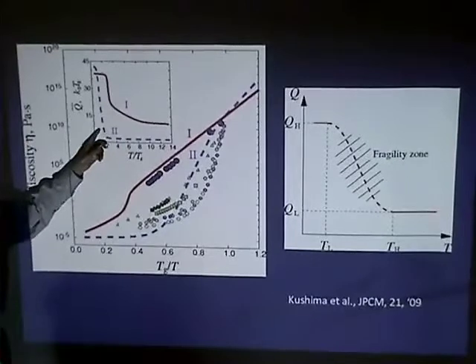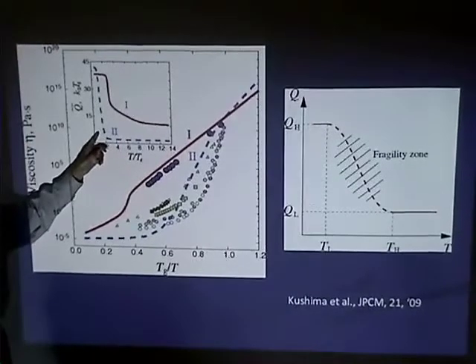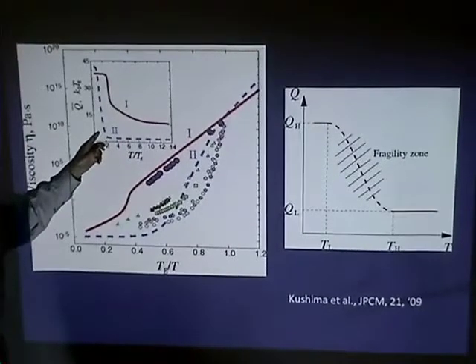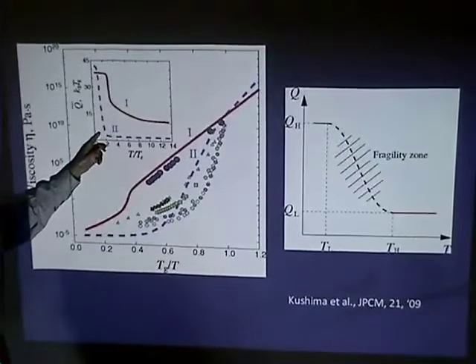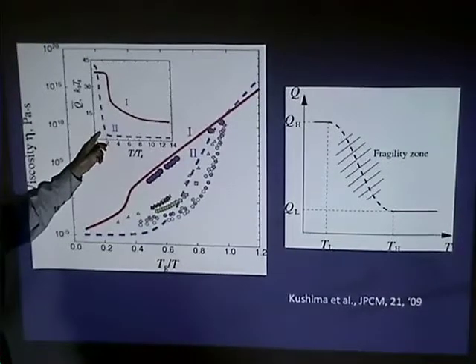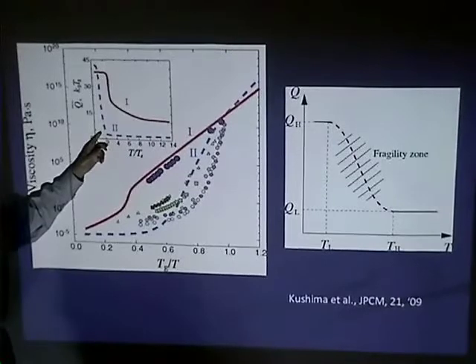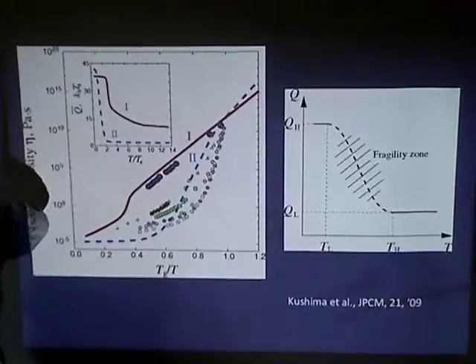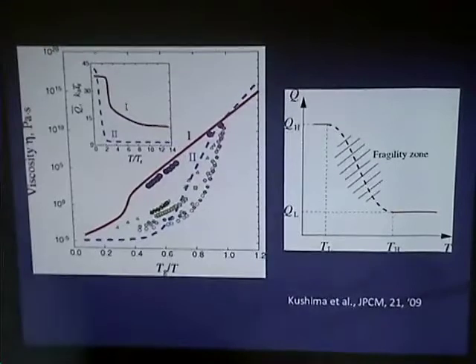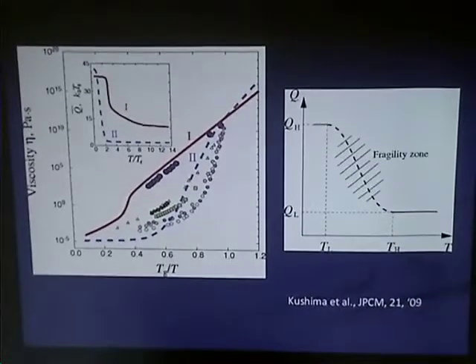What's going on is that as you lower the temperature, the system is able to find deeper and deeper wells - that's systematic, that tracks, that's why the activation energy goes up. So basically, if you do your steepest descent quench and talk about fictive temperature, if you start out with fairly high temperature you'll find some low-lying things. But if you go to lower and lower temperatures, and if you do enough statistics, you will find deeper and deeper wells.